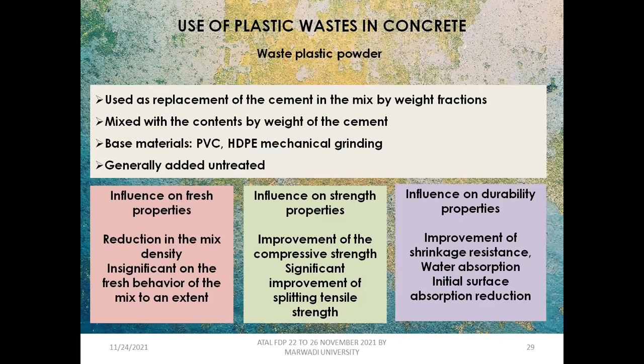When you are going to use recycled plastic powder, making sustainable concrete material, it influences in a different way the fresh properties, like reduction in the mix density, insignificant on the fresh behavior to an extent, so we can definitely promote it. On the other hand, improvement of the compressive strength, and significant improvement in the splitting tensile strength that we have noticed. So again, we can definitely use this format of the waste plastic in the concrete as a powder. But definitely you need to work upon the optimum contents in the mix design. That is the catch of all this work on which you have to focus.